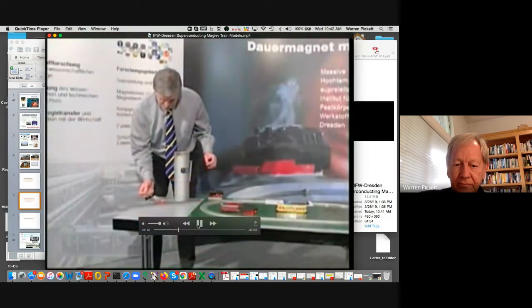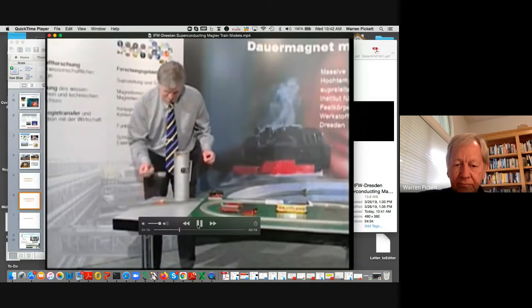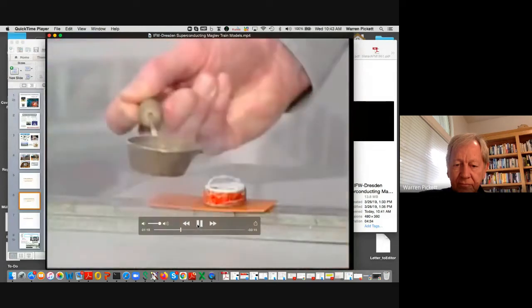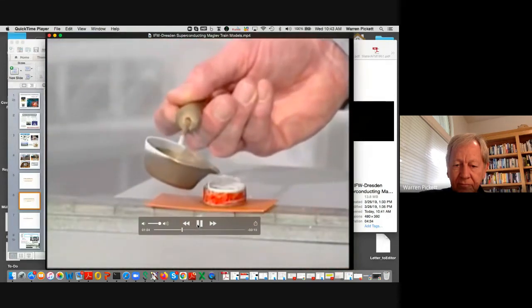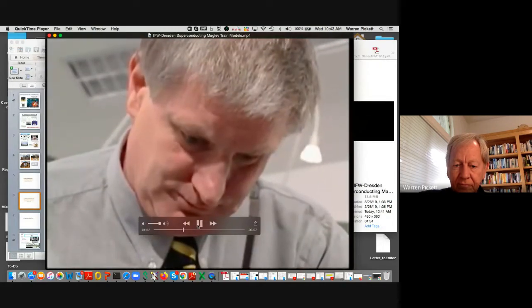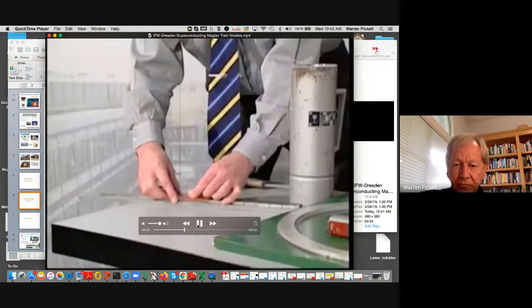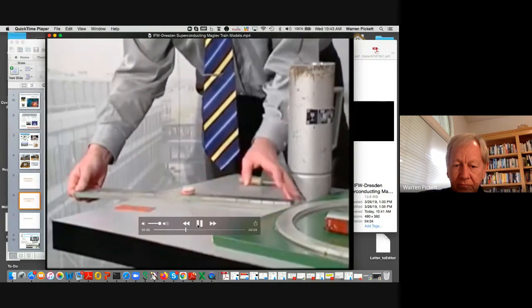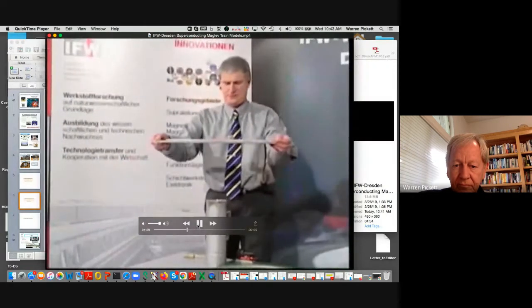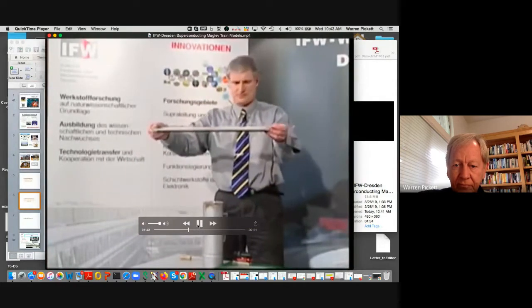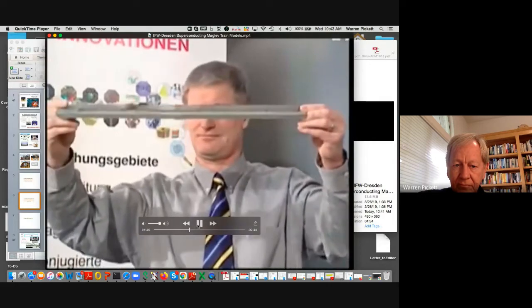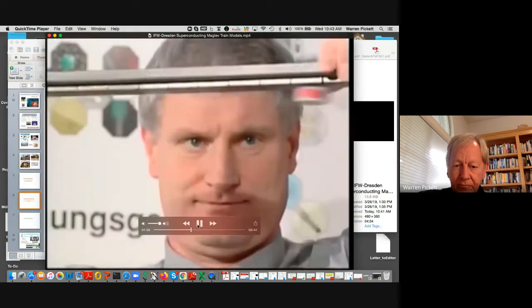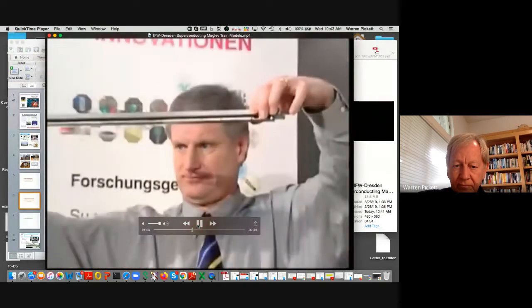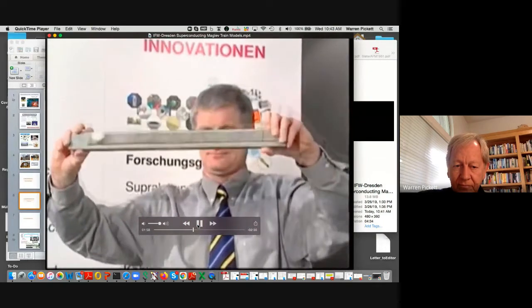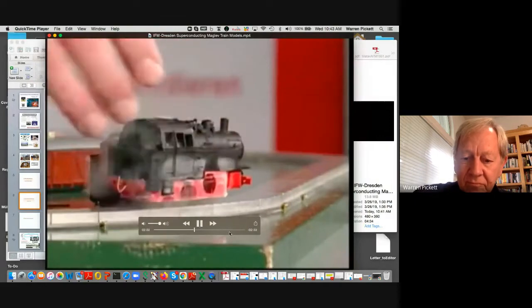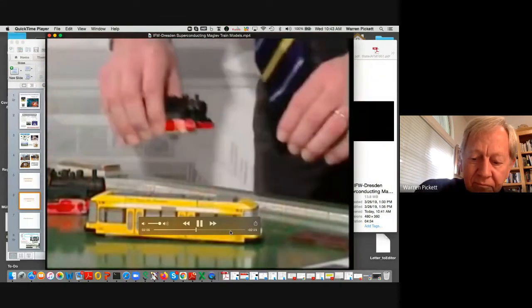An impressive experiment is designed to demonstrate how strong the forces are which hold the superconductor on the track. The superconductor is brought into a certain distance of a few millimeters above the magnetic rail and cooled down in this position using liquid nitrogen. Reaching the specific transition temperature of minus 183 degrees Celsius, the superconductor traps the magnetic flux of the outer field. Now we can remove the shim of a certain thickness, which determines the distance. The superconductor has now memorized its position within the field of the rail. The superconductor is fixed at this distance and can only move along the magnetic rail, even when turning upside down. But the effect lasts only as long as the superconducting state in the material is maintained. To set the superconducting levitation train in motion, one has only to give it an initial impulse by hand.